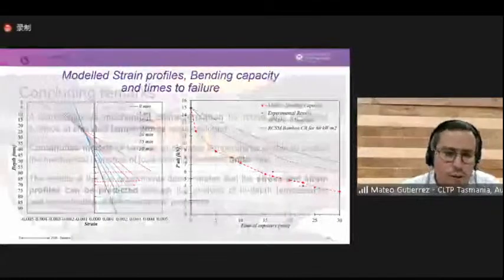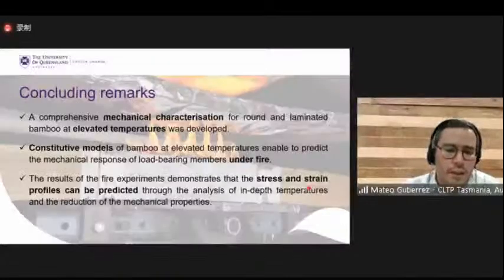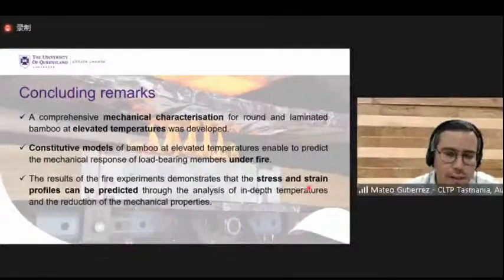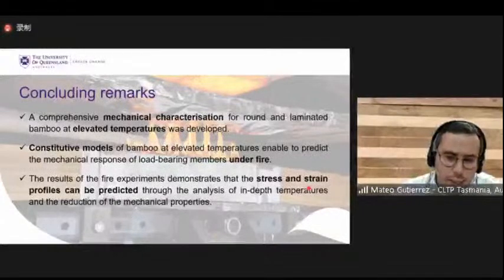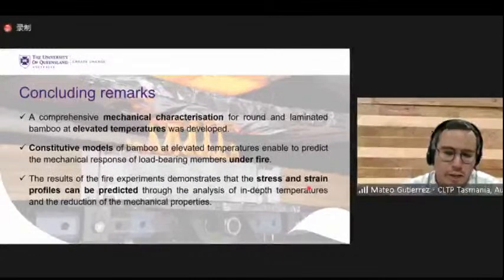So in conclusion, during this research, we did a very comprehensive characterization of bamboo at elevated temperatures. We created some constitutive models that will help us to predict the performance of load-bearing bamboo members under fire. These results demonstrate that stress and strain profiles can be predicted through the analysis of in-depth temperatures and the reduction in the mechanical properties.